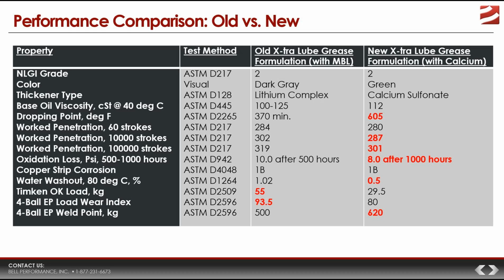They then cool it and weigh the whole thing to determine the amount of grease lost during the water washout scenario. Comparing the old grease with the new grease, you can see that the new X-tra Lube grease loses less than half of the amount that the old grease loses. That makes advantage number 4, better water washout performance, to go with the previous 3: dropping point, better shear stability, and better oxidative stability. So already you've got 4 major things that show that the performance of the new X-tra Lube grease is significantly better than even the old grease.